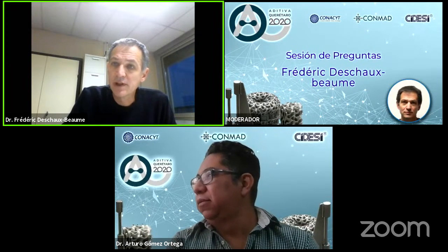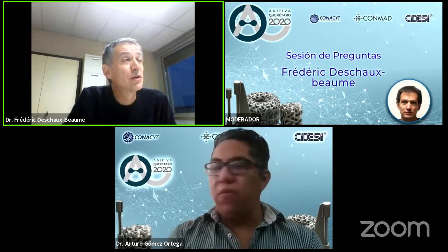It depends. The surface state is rather bad with this process, so a finishing by machining is often required. So the surface state is not really a criterion. For an order of magnitude, the ratio between height and width may be 0.5, maybe 0.3 to 0.5. For a width of about 5 to 6 millimeters, we can obtain a height of about 2-3 millimeters with a rather good shape. Okay, thank you.